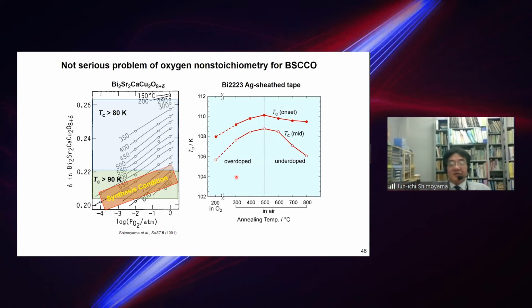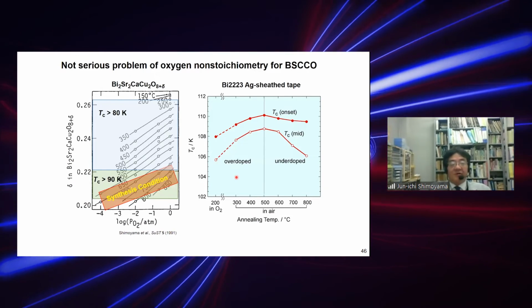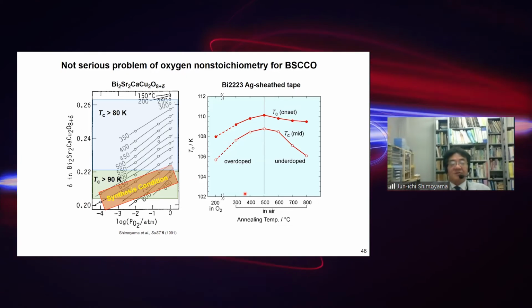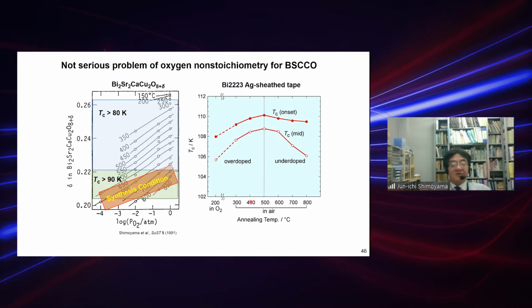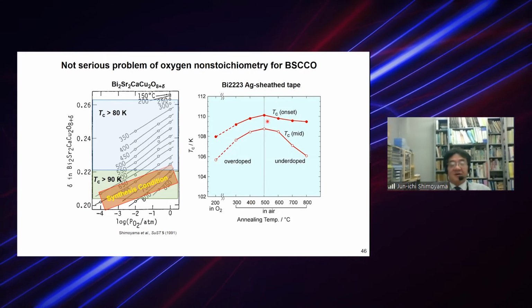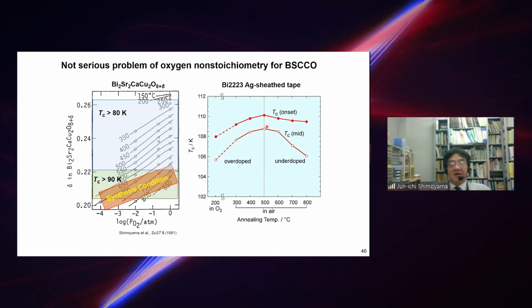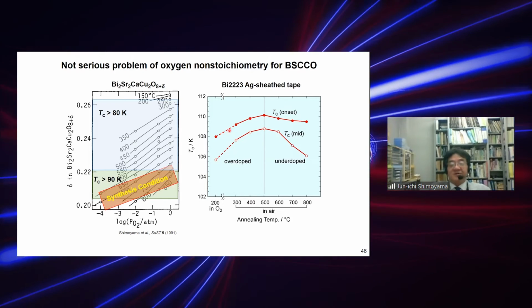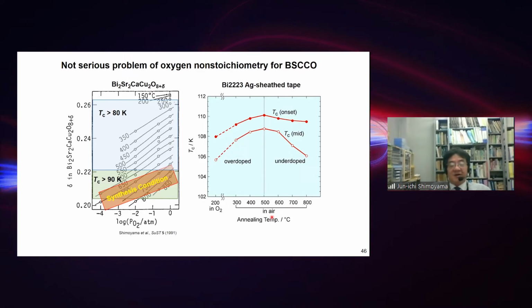But in the case of the Bi systems, we don't need to worry about oxygen content. This is a much different case from the REBCO or layered systems, because the Tc is not so sensitive to the oxygen annealing temperatures.